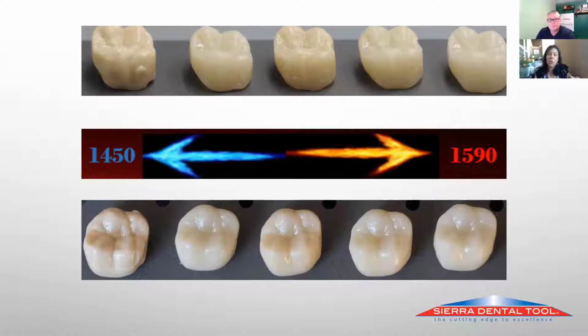So we're only 20 Celsius away from the recommended temp. But what happens is you go from really white and chalky, and when you're really close to the high temp but slightly under, you end up with more chroma, but still high value. So a lot of people will describe that as my crown is too dark. And yes, it is. It has too much chroma. It really needed that 20 Celsius to achieve the proper shade. So the fourth crown is the proper outcome, what we're looking for.